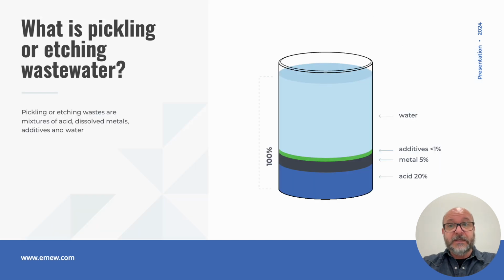Pickling or etching wastewater is simply the liquid waste solution that's generated from the pickling or etching process. More specifically, it is a very toxic and corrosive solution containing a significant portion of strong acid. This could be sulfuric, hydrochloric, nitric, or combinations thereof, typically on the order of 5 to, in some cases, greater than 20% of concentration by volume. Dissolved metals, these could be iron, nickel, chromium, copper, zinc, etc., from 1 to as much as 5% by volume, and trace organic components such as surfactants, antifoams, inhibitors, or levelers, typically in trace amounts. In industry, pickling or etching wastewaters are commonly referred to as either being spent solutions or acidic rinse waters, depending on where the solution originates from in the process.